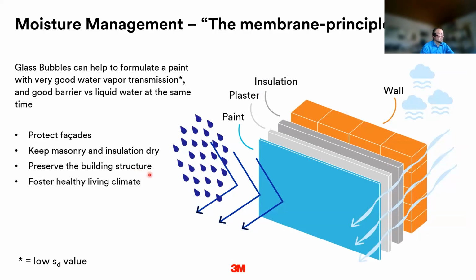And last but not least, what's also very important is the moisture management. It was shown in several studies and experiments that glass bubbles can help to formulate paints with very good water vapor transmission properties, so low SD values, while it was still possible to have good liquid water barriers at the same time. And that's important to get the facades protected and also to keep the masonry and the insulation dry, because the vapor can move through the coating, through the paint. That will eventually preserve the building structure and also help to have a healthy living climate inside your home.